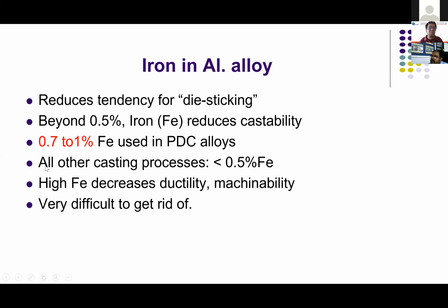With 0.7% iron, it is very easy to release the casting. So therefore, we have to improve the die coating, the die spray to release the casting. Don't add iron for releasing. You are adding only a material which is very cheap. You are reducing the cost of the alloy. At the same time, you are incurring a problem of the casting, which becomes more brittle. Most of the process uses less than 0.5%.